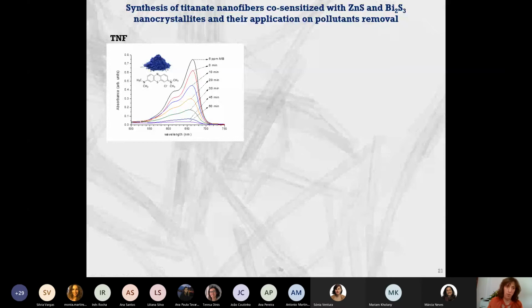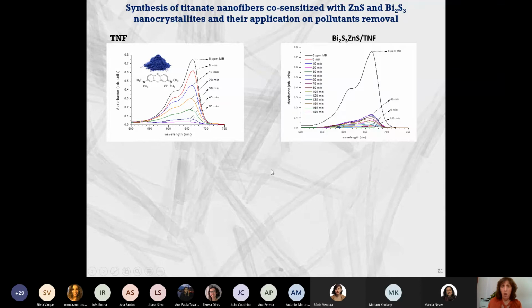way to see these materials. Imagine that we test these titanate nanofibers to remove, in this case, methylene blue dye. So this is normal degradation. You turn on the light and you start to decrease the amount of dye that you have in solution.